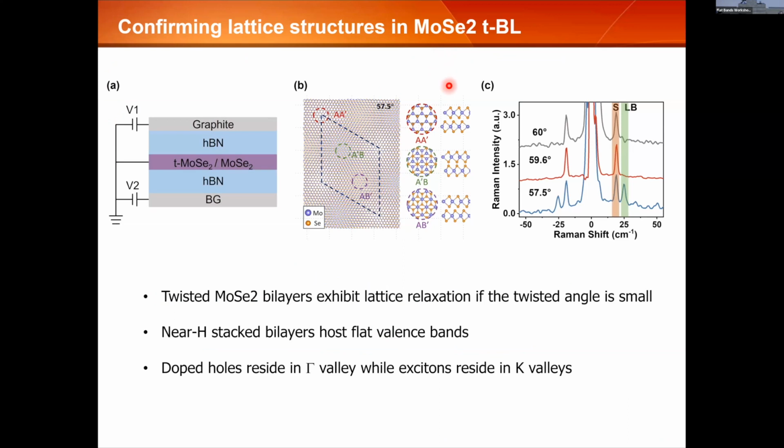As has been mentioned a few times, these twisted bilayers at very small twist angle have lattice reconstruction that leads to completely commensurate AB and BA stacking within the domains and high energy AA stacking at the domain walls. So only when you increase the twist angle, in this case, away from about 60 degrees, or H stacking, by 2.5, we start to see this gradual atomic variation. I think this gradual atomic variation is important to also observe basically what Xiaodong has talked about, the interlayer pseudospin,